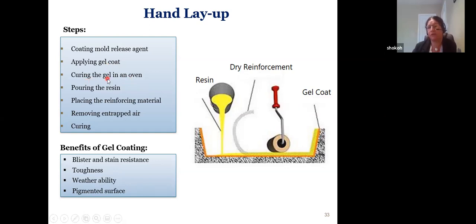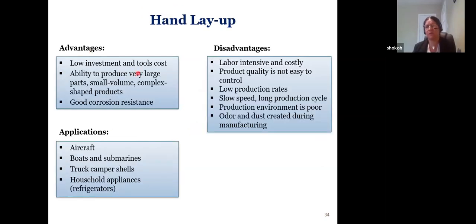But you need to cure it, for example at elevated temperature in an oven. And when that's done, you add your resin, which is thermoset most of the time, and then you put the reinforcement on top of it and brush it to remove any bubbles or entrapped air, because those will be defects in your composite. Then you let it cure at ambient temperature, though a lot of the time maybe you need to heat it up. This is the hand layup process, very simple. The advantage is low investment and low cost tooling. You can produce very large parts like boats, and very complex shapes, and in a lot of places where we need corrosion resistance, we use hand layup.